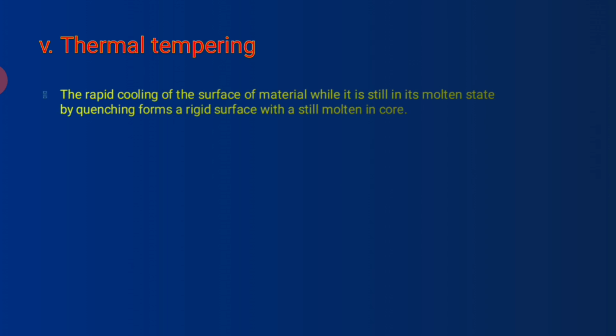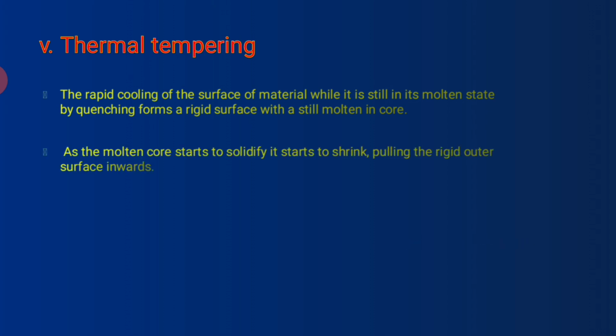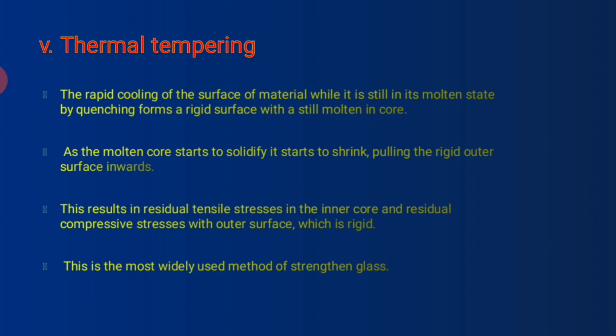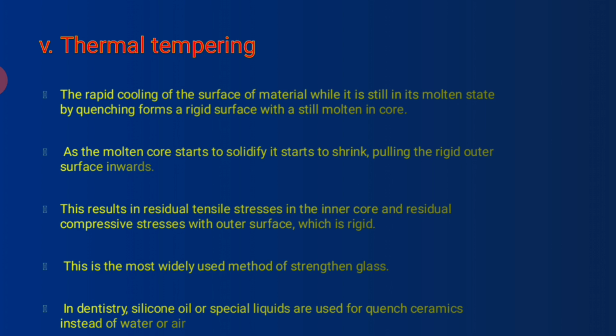So the rapid cooling of the surface of material while it is still in its molten state by quenching forms a rigid surface with a still molten core. As the molten core starts to solidify, it starts to shrink and it pulls the rigid outer surface inwards. This results in residual tensile stresses in the inner core and residual compressive stresses with the outer surface, which is rigid. This is the most widely used method to strengthen glass, and in dentistry, silicone oil or special liquids are used to quench ceramics instead of water or air.